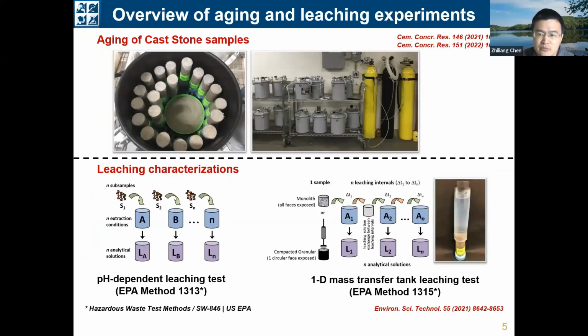So this is just a brief overview of the aging and leaching experiments. For the aging of the Cast Stone, the samples were put into containers and then maintained under different aging conditions for different periods of time. And the aged samples were then used for the leaching characterizations. And based on the experimental results, different models have been developed. And more details regarding the model development can be found in these several papers that we have published.